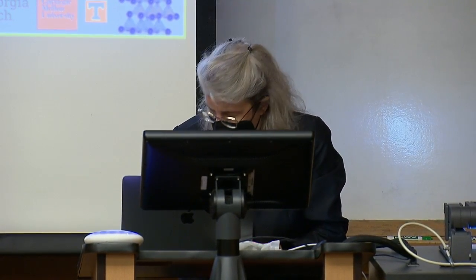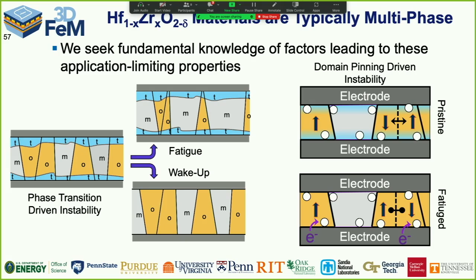But once you get to that antipolar state, under the appropriate levels of strain, you get all of the ferroelectric states coming out. And so that's what you're seeing out here, all of the possible orientations for that polarization. And it depends, tragically, on absolutely everything, including the point defect chemistry. So many of you will have taken Professor Trolier-McKinstry's electroceramics course. What do we use fluorite structured oxides for?